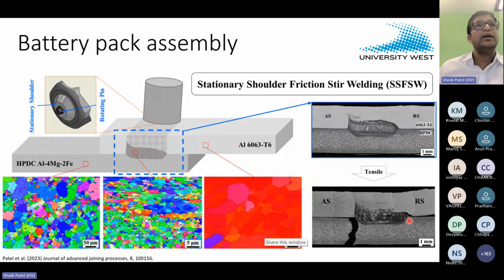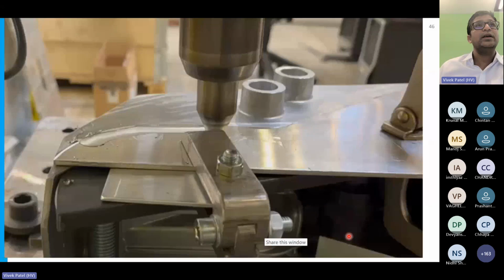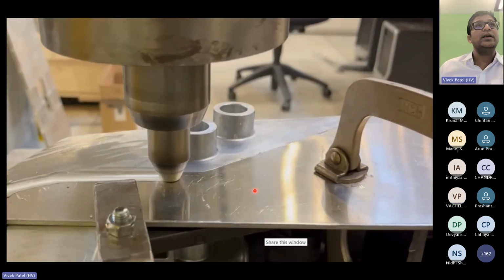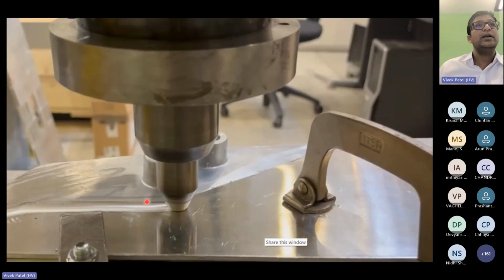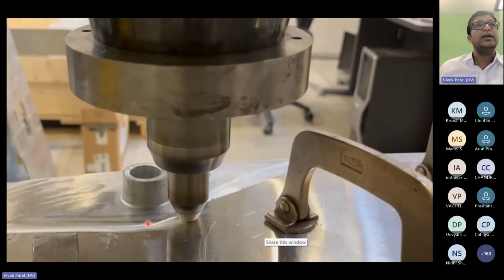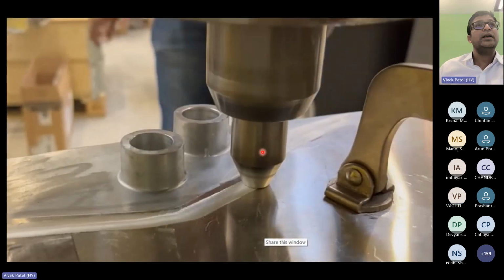And when we tested after process parameter optimization, in tensile testing you see that the weld was trying to open from the retreating side. It's a typical cold lap feature of lap joints in friction stir welding. But ultimately, the final failure happened near the hook side of the cast material, as expected. And then in some of the videos you can see how close we are welding. So here on the top, you have the extruded material, and this is a cast component. And here we are welding very near to the edge in 2 dimensions.